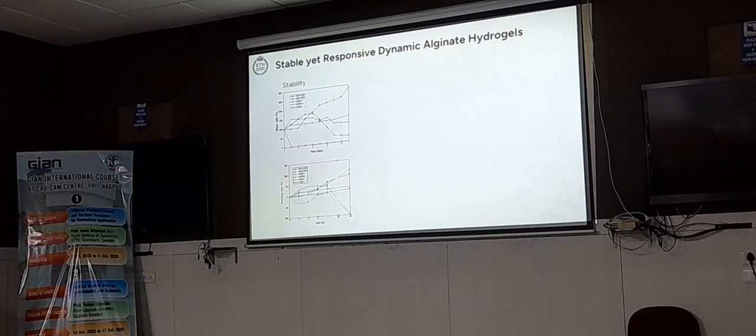And we could see that we had the right ideas. I will tell you what this says. If you have the crosslinkers that are not attached to the alginate, then the stability is very low. The one here in the bottom, where you have the red and blue, that is the ADH and PDO where you just have the crosslinkers added. The stability there is quite low. If you have the one that is attached to the hydrogel on one side, then you have a higher stability.